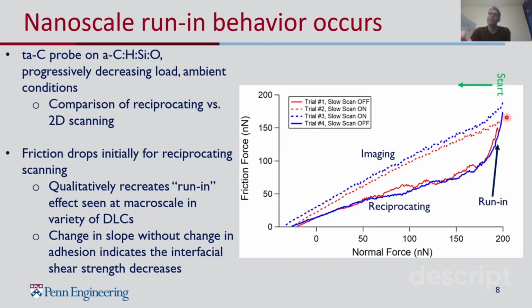If we switch to looking at the reciprocating sliding result, we see very different behaviors. The initial friction starts at a similar value, but then it drops rapidly. And so this rapid drop in the friction, we think, is akin to what is happening in the macroscale run-in process. There's some initial transformation of the sample surface that causes the friction to settle into a lower value. So we think we're capturing some of what happens with the run-in process. Additionally, since we know by repeating these trials multiple times with the same result that the tip geometry is not changing, what that means is that at a given load, there's the same real area of contact between the imaging case and the reciprocating case. And given that the friction is at a lower value, that means there's some change in the interfacial shear strength that's happening as a result of this run-in process.